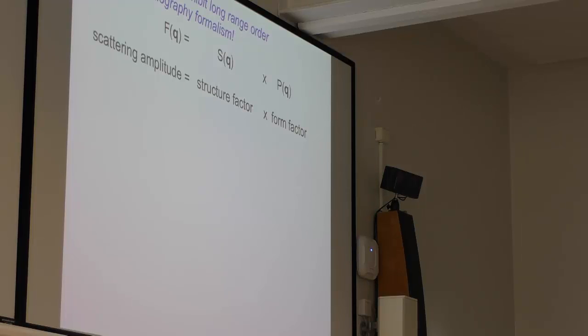And because of this, we can take the formalism that is well known from crystallography, where we just replace the form factors that are usually just describing the form of an atom, so it's typically just some isotropic scattering function, right? With a function which actually describes the shape of the pores that we are looking at.